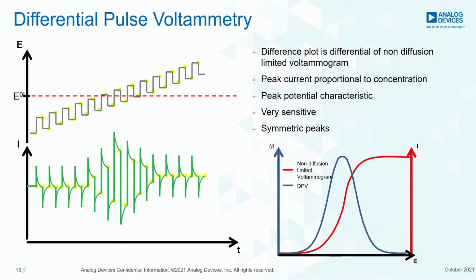And what we do here in differential pulse voltammetry, we don't plot the current, but we plot the current differences right before and after the pulse. This is the nice effect that we get rid of some physics effects and only look at the chemistry. And what we get this way is, well, we also get a differential plot of what a linear sweep usually would be, which has the advantage that we get a symmetric peak, we get a peak that is proportional to the concentration in our solution, and as I mentioned, it's very sensitive.